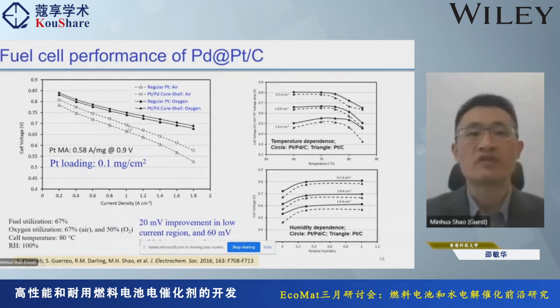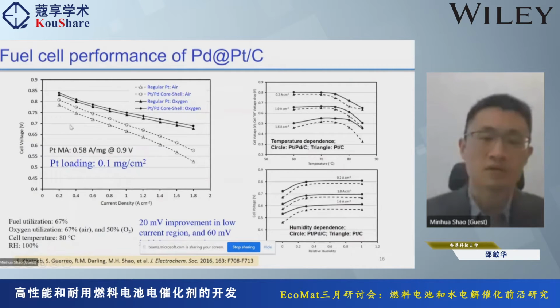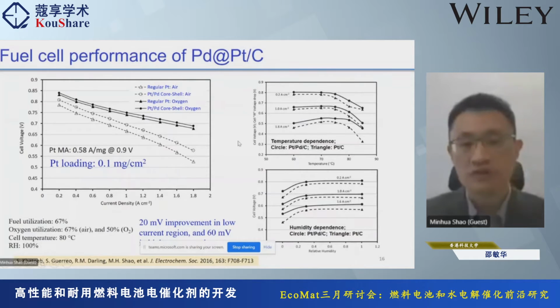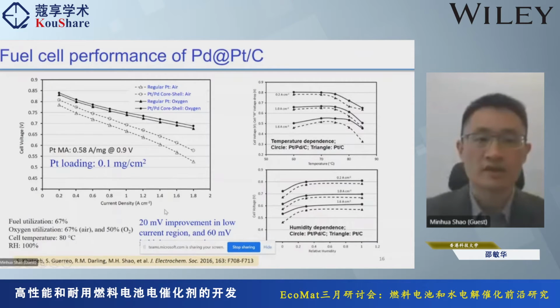And we did this fuel cell performance, compared with platinum benchmark, in both air and oxygen. The solid line is in oxygen and the dashed line is in air. This data was published in 2016. At that time, it had not been optimized, but it is at least clearly showing that there's this improvement over the benchmark of platinum. So that's the first time that we demonstrated that the core shell, not only in the RDE testing but also in the real fuel cell, actually has better performance than the pure platinum.